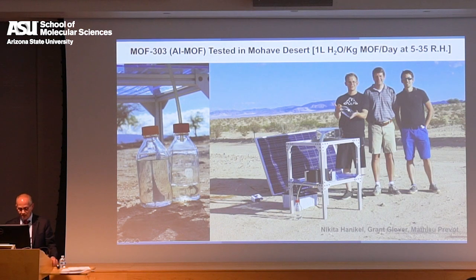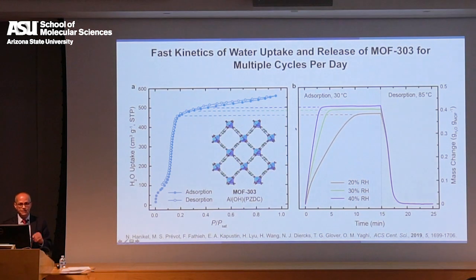So the nice thing about this is that the MOF stays in the device for many years, right? Because we've already tested this MOF over 36,000 cycles, and the water leaves no imprint on the MOF. The MOF performance is reproducible. And the very nice thing about this is that the water comes out of the pore with great facility. At 85 degrees, you can remove the water from the pores in less than 5 minutes, okay? Just a few minutes. If you don't want to go to 85, you can go to 60, but that means you have to do more cycles, or slower cycles, excuse me.